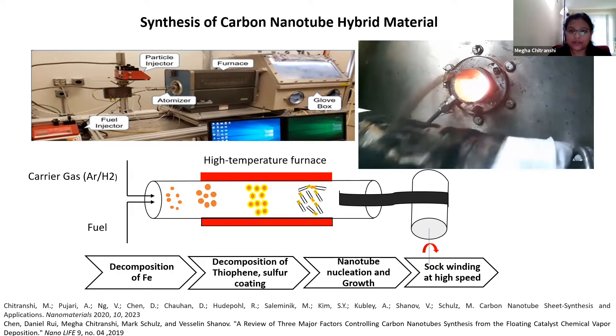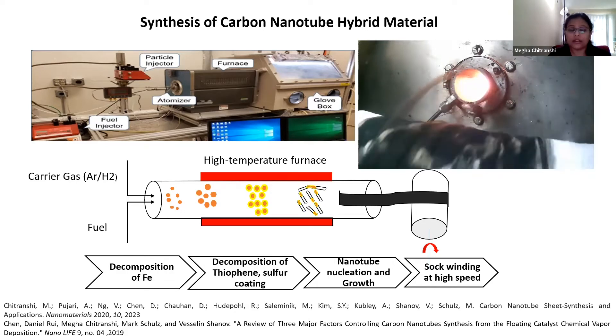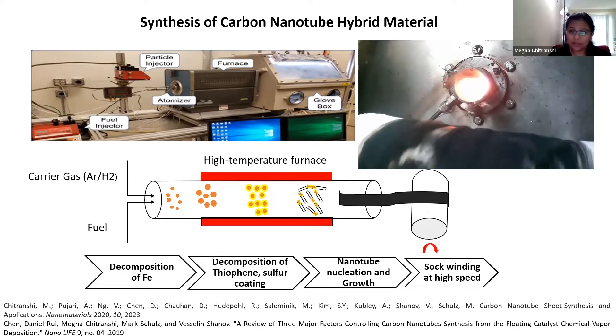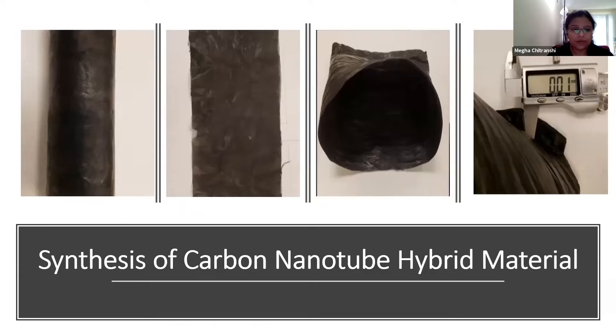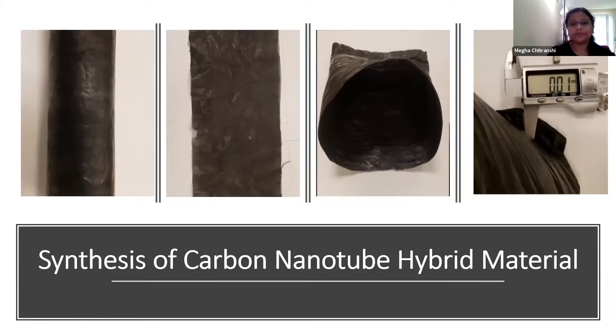This process is highly customizable. There are many variations — you can vary the synthesis temperature, the carrier gas flow, and the winding speed of the drum, just to customize the product you want. Here are some images of the carbon nanotube hybrid material: the first two images show tissue CNT, the next two show carbon fiber CNT cylinders. As seen in the last image, the thickness of the material is around 10 micrometers, and typically materials range from 10 to 20 micrometers. The thickness is variable — it is a customizable material you can synthesize to suit specific applications.